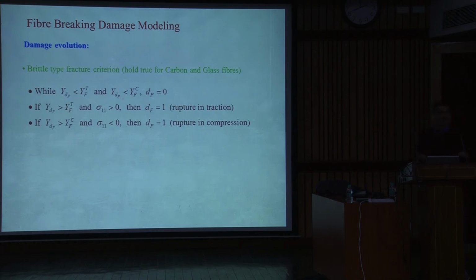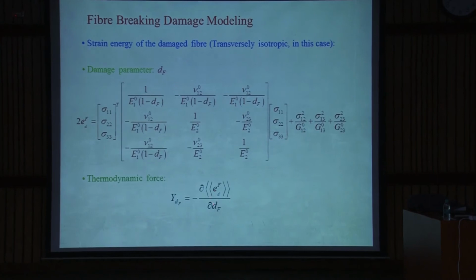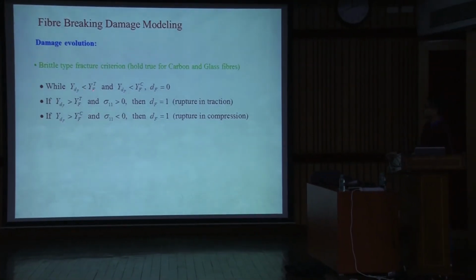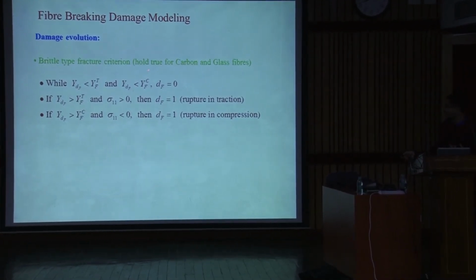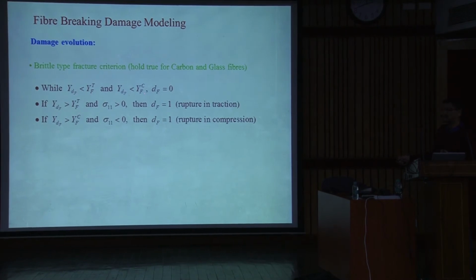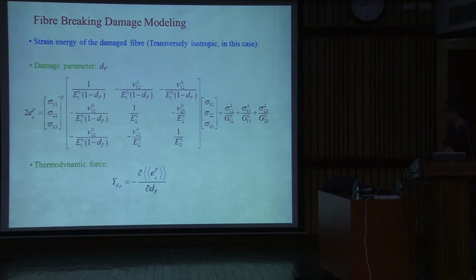So how do you evolve the damage? You are talking about when it is going to happen, and when it is happening, how it will propagate. So you are talking about the initiation to its last stage. In this case, for the fiber, you are talking about this thermodynamic force. If this thermodynamic force, whatever you got here, is less than the critical thermodynamic forces in tension and compression, YFT and YFC, which correspond to the maximum strength of the fiber in tension and compression. I can do a similar thing here for maximum stress in the fiber, for tension and compression. So that is basically the fiber strength in tension and compression.